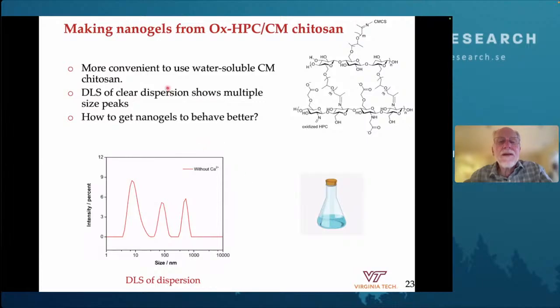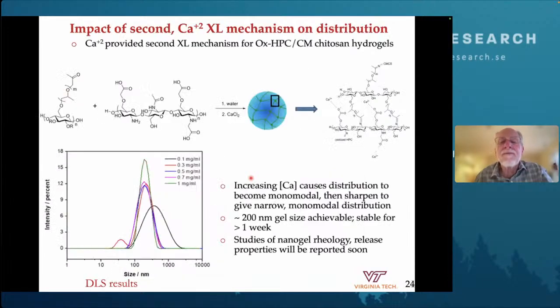We thought it would be more convenient to make those nanogel dispersions using carboxymethyl chitosan, getting rid of the acetic acid. We tried that, and we got a DLS figure showing multiple peaks of different sizes, meaning we're not getting well-behaved formation of nanogels when we use the carboxymethyl chitosan. So what to do about that?